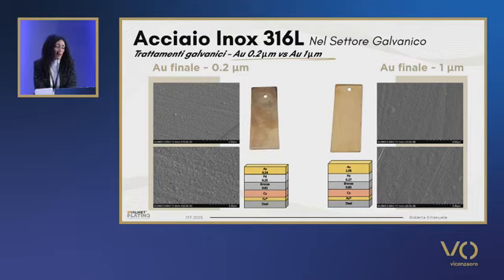In the literature, we read that with layers less than 0.8, we have a great porosity. And you see the image of a sample that has been coated with 0.2 micron of gold. And on the right-hand side, you see that pores are visible. And it is probable that from these pores, the nickel gets to the substrate. So a thicker layer prevents these pores from occurring and prevents nickel from getting to the surface.